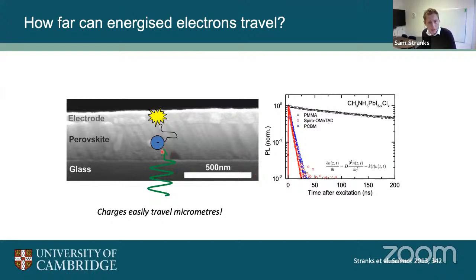So this is looking at cutting a perovskite cell in half and looking at a cross section again. And what we do is we put a pulse of light in at the bottom, a very fast pulse that's 100 picoseconds, which is 1,000 billionth of a second, so a very, very fast pulse of light, and we watch the light coming out. And so we can look at decays over time. So this is looking at the light over nanoseconds, so over billionths of a second, how these carriers decay away. And when they decay away, they emit light.